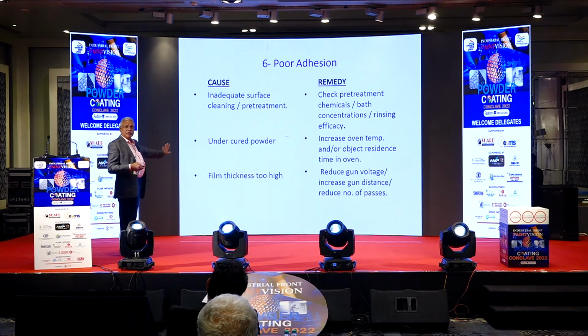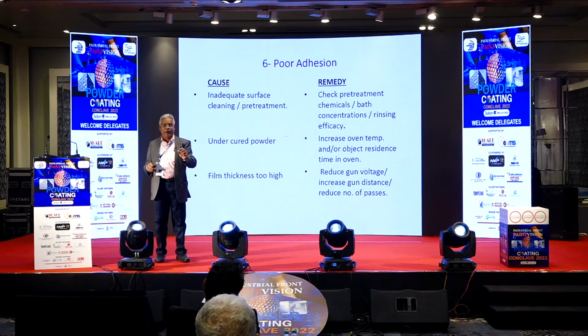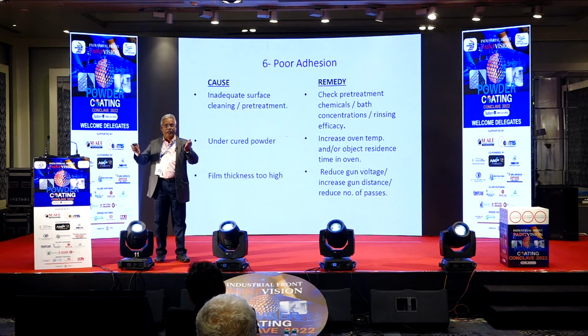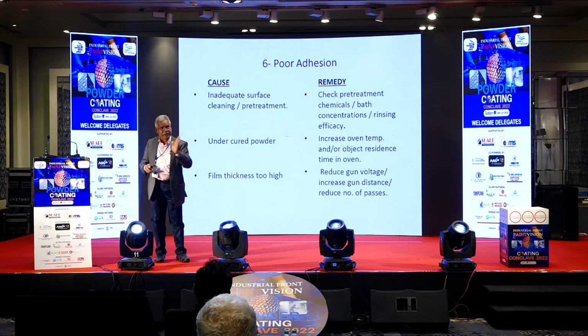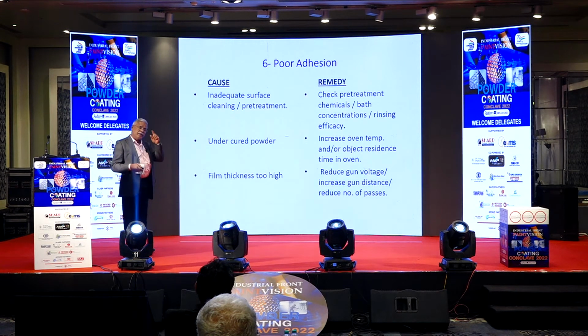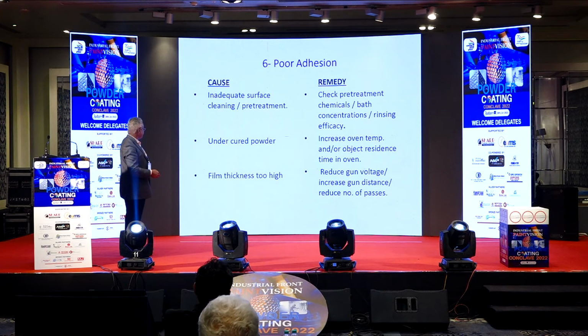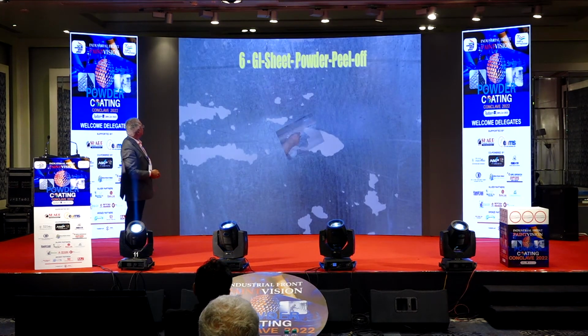Undercure: the powder does not reach full temperature. Suppose it is a thick component; if they put it inside the oven and the temperature does not reach 180 degrees at 12 minutes, then also the surface coating, if the coating thickness is high, the core will absorb the heat into the metal. So the surface will not retain that 180 degree temperature. It will reduce because it is absorbed by the thick material. In those cases, you have to make a trial first and then decide whether to increase the time. You have to ensure that for thick film coating.